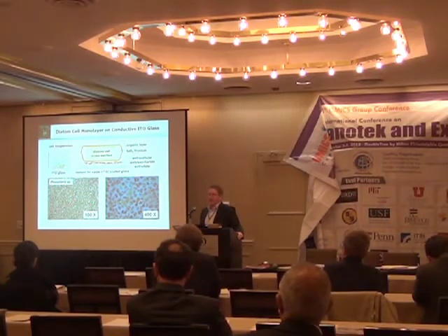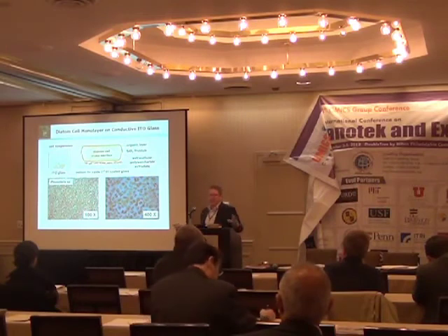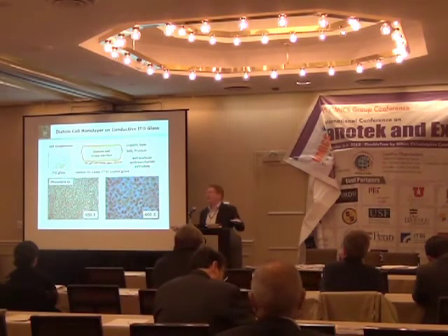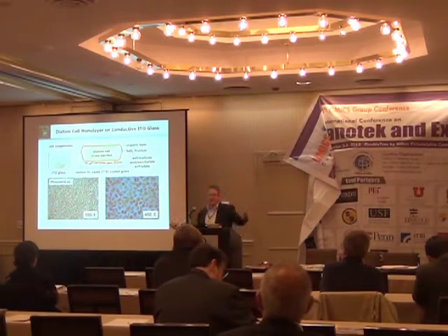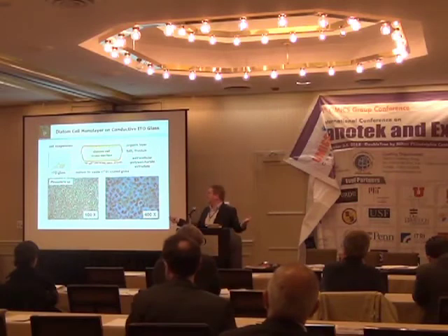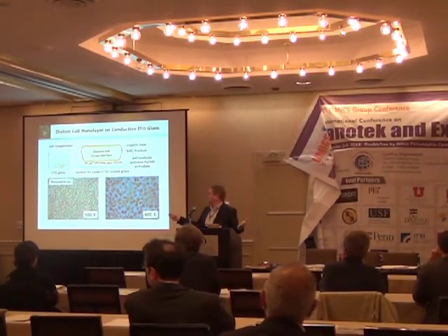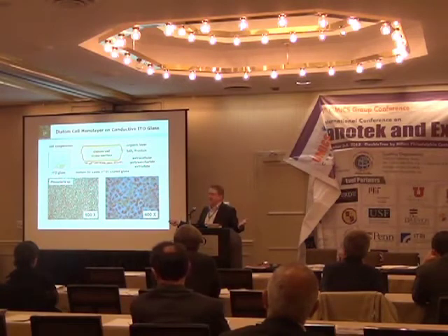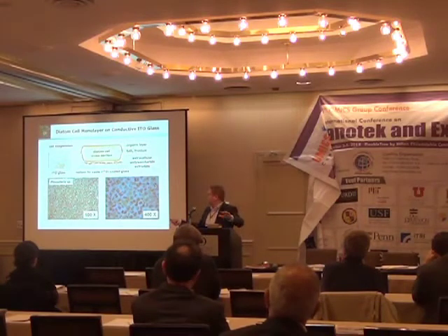In order to enable this process for integration into devices, one would put this ultimately onto a thin film. And the way we do this is actually pretty simple. After we grow up the cells, we just put in, for example, conductive glass that you could use as a substrate for various optoelectronic device fabrication. And the organisms will actually settle onto the glass, and they'll move on the glass here. I don't have a movie to show you like the previous speaker. But they'll actually move and self-assemble into a dense film.